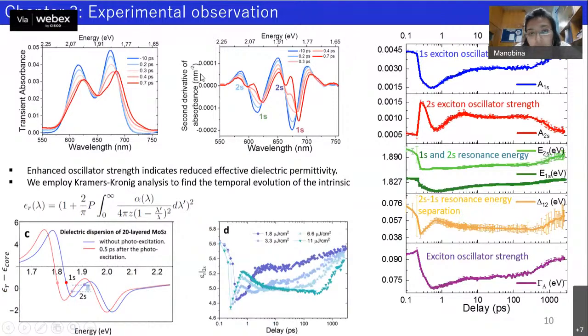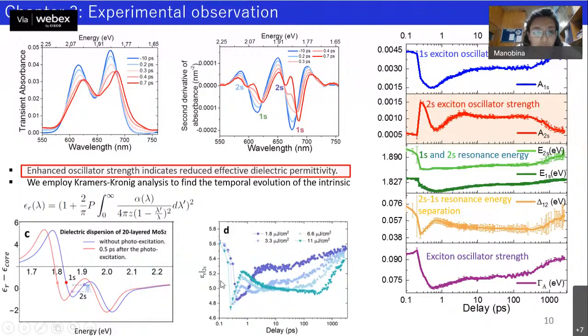Now after photoexcitation, the absorption reduces in this excitonic features, but interestingly we observe that this first excited state, which is known as 2S state, absorption increases after the photoexcitation. So this is an aberrant result, and to find this origin, we employ this Kramers-Kronig analysis and find the change of the dielectric permittivity over time. So we observe that this 2S exciton state, the permittivity at this resonance undergoes some reduction. So due to this reduction, we observe this enhancement.